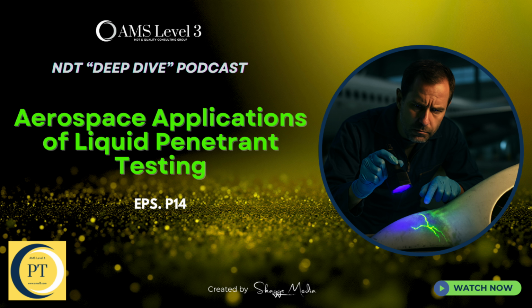Okay. And second, a lot of parts coming from service have contaminants, oxides, acids trapped in the crack that physically repel the penetrant even after cleaning. So just letting it sit there, the static dwell, isn't aggressive enough to get in. The solution in the source is to use ultrasonic pumping. Correct.